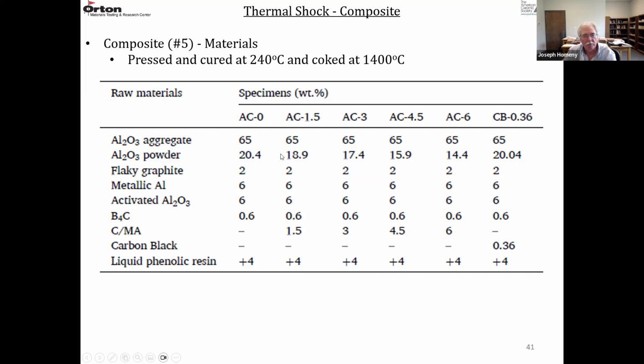So they dropped the amount of finer aluminum oxide powder as they added the carbon spinel. So MA is the magnesium aluminate spinel. So they added these powders from 1.5 to 6, and that's indicated on these different labels. So they dropped the aluminum powder and added this spinel powder in its place.